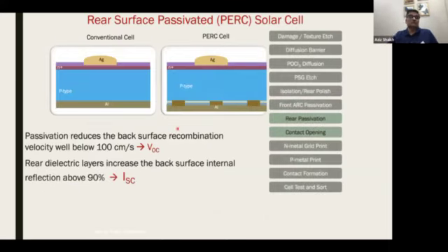So how does this structure look? This is a cross section. This is the P-type wafer, this is the N junction, this is silicon nitride, this is silver. On the back side, you have aluminum, and then you have the bus bar. This is the standard conventional BSF cell. In PERC, you put a passivation, which is aluminum oxide passivation, and then you form a localized BSF. You open this passivation by laser, so you hit the laser to create holes in the passivation. So you need to have both the BSF, back surface field, as well as back surface passivation.